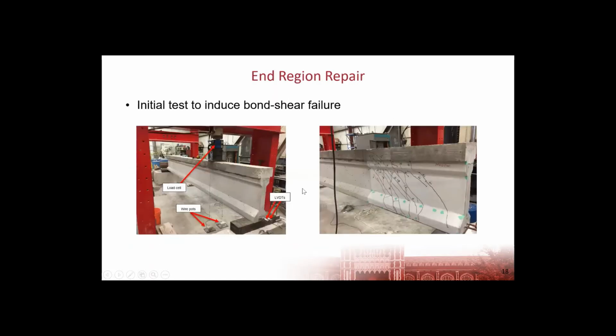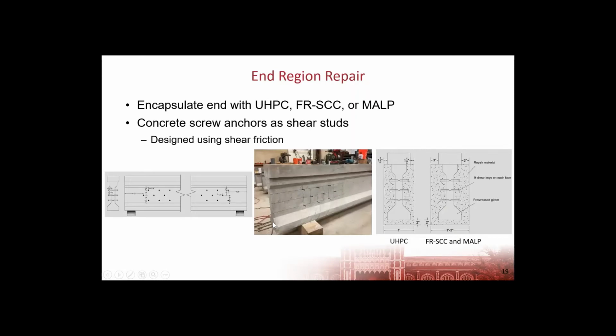So specifically for the end-region repair for shear damage, or you could think of this as shear strengthening, we did an initial load test to induce a bond shear failure. So again, close to the end region, potentially could be affected by corrosion at the ends. We loaded to failure, and our failure criteria was based on the maximum deflection as well as the anticipated load. Afterwards, we mapped all the shear cracks so that we could compare to the post-repair load test that we would do eventually. And then once we had our induced damage, we went in and encapsulated the end region using either the UHPC, FR-SCC, or MALP concrete.